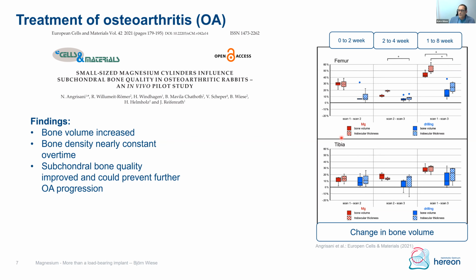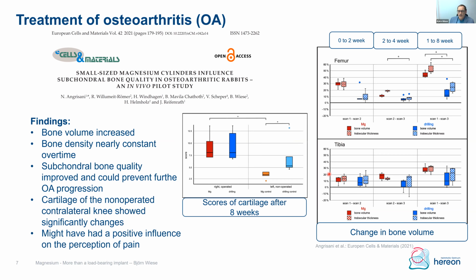At the same time, we're getting a more stable trabecular thickness. That means it could prevent future osteoarthritis progression. This happens quite close to the implantation site on the operated knee of this rabbit, but we're also seeing some effect on the non-operated knee. That means the magnesium ions that got released seem to also have an impact on the cartilage, in our case on the non-operated knee of our rabbits.